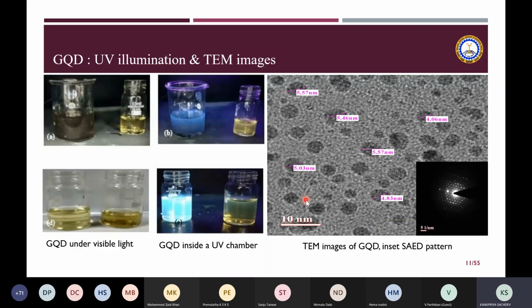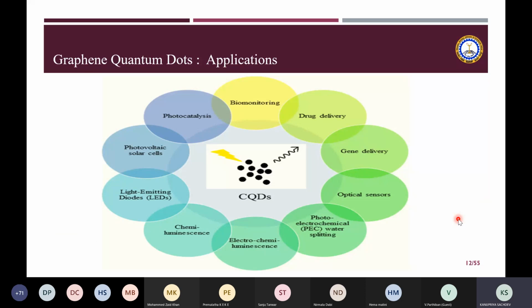These are the solutions. We could not filter them because we didn't have the right membrane. So this is a solution of the graphene quantum dots under visible light. This gives you the graphene quantum dots in a UV chamber. And these graphene quantum dots were then analyzed by the transmission electron microscope. And you can see that the size of these graphene quantum dots is less than 10 nanometer, and a very good crystalline behavior is seen in the SAED pattern in this inset. So these graphene quantum dots find lots of applications: photocatalysis, biomonitoring, drug delivery, gene delivery, optical sensors, water splitting, electrochemiluminescence, chemiluminescence, LEDs, and photovoltaics, solar cells.